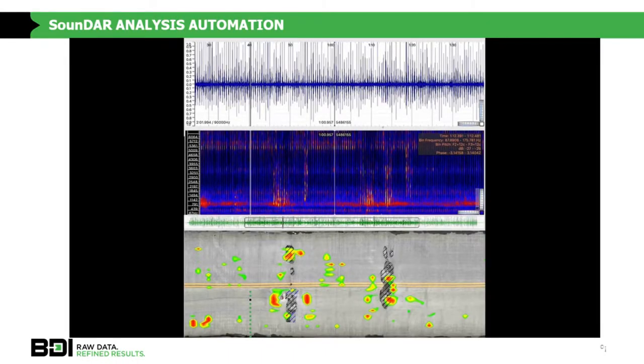Through the research process, we did lots of manual chain dragging and coring to validate that identified signals are indeed delaminations. The noise floor is where we're typically seeing traffic; the high-frequency area is too high for the human ear. The areas in the middle are right where the human ear would identify delamination. The method is repeatable and very reliable.